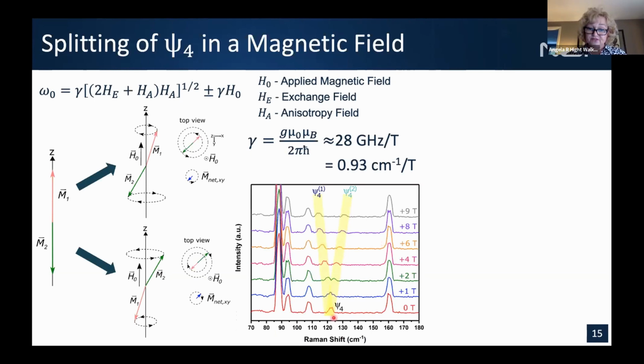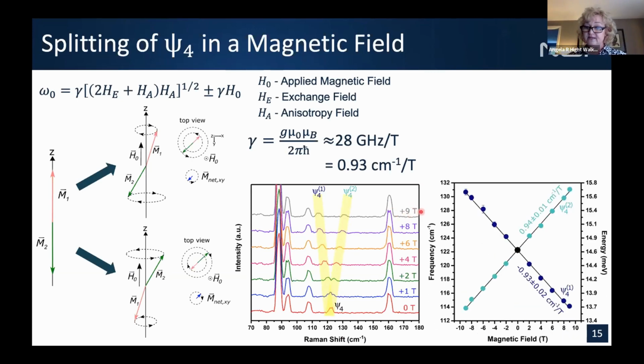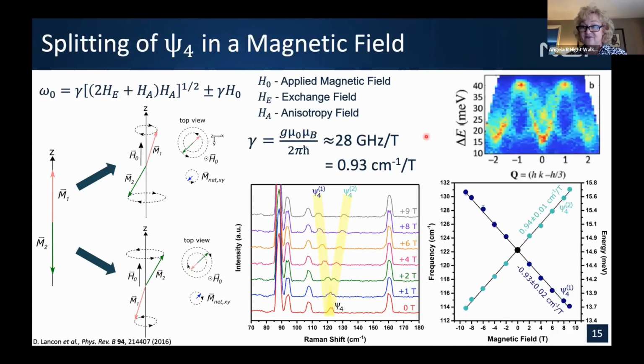So again, with our unique setup, we can do this. Here is an example of Psi4, and again, the signal to noise is very small, but you can definitely see these two features being resolved. And up here, that's at 9 Tesla. So we did it both in the positive and negative magnetic field and fit the lines, and it is shockingly good. So this was quite comforting that, in fact, this feature is a magnon.